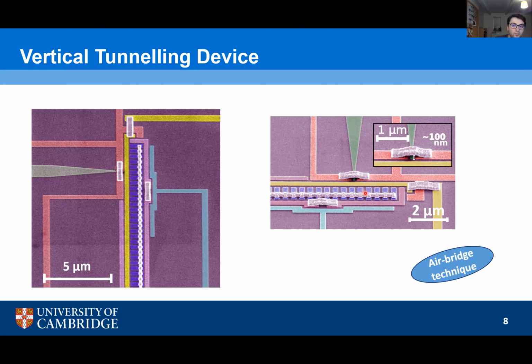So like I said, the 1D region is in here, but in order to inject current into the wires, you have this 2D region. And by having a gate there, you can move this region around and map it separately and subtract it from the data. So we can only look at our 1D-2D tunneling signal instead of having this parasitic signal on. And that was an improvement we were able to do because of this gate here.